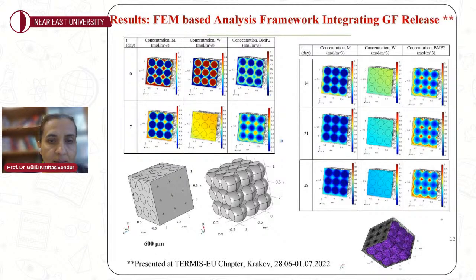The first column of data represents the concentration of the polymer scaffold made of PCL that had pores in the form of spheres. You see the mesh on the bottom right here. The water concentration with respect to time, where this is the initial state of the water concentration, the 7th day, 14, 21, and 28. We do see that the polymer concentration is undergoing both surface and bulk degradation.